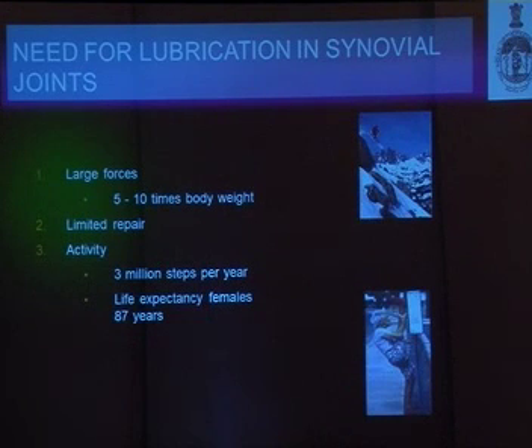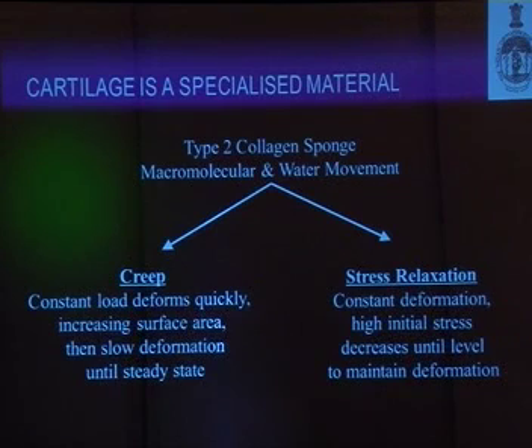Why do we need synovial fluid or lubrication in synovial joints? We know the knee or the hip normally takes 5 to 10 times the body weight, there is limited ability of the cartilage to repair itself, and we walk almost 3 million cycles or steps per year. And of course, as life expectancy increases, our cartilage is undergoing more stress. The cartilage is a specialized material. It has type 2 collagen and it has creep and stress relaxation. Creep is under constant load, it deforms quickly, increases the surface area and gradually deforms slowly till it reaches a steady state. Stress relaxation is under constant deformation, with high initial stresses that decrease gradually to the level needed to maintain the deformation.